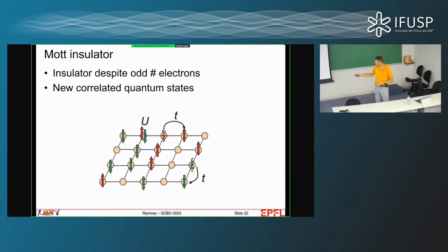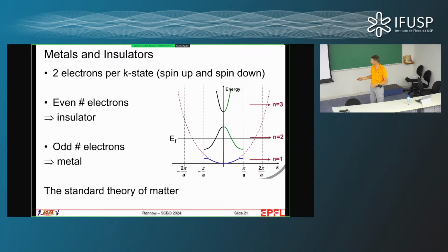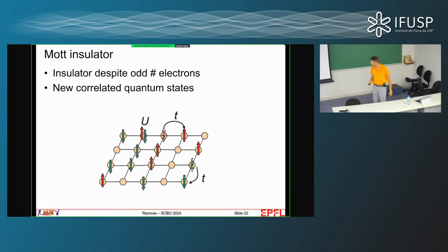And possibly the simplest example of that is you take a square lattice like this, and you put electrons on the square lattice. Now, if you put exactly one electron for each site, in principle you now have an odd number of electrons, and according to what I just said before, you should have a metal, right? So basically, you should be able to have a current flowing with just a small electric field applied to the system. However, what happens is that because you have a Coulomb interaction on each site, given by an energy scale U here, if that's large, then actually the electrons will repel each other and they will get stuck. And if I have exactly one electron on each lattice site, it's a little bit like a traffic jam. There's no place to go.